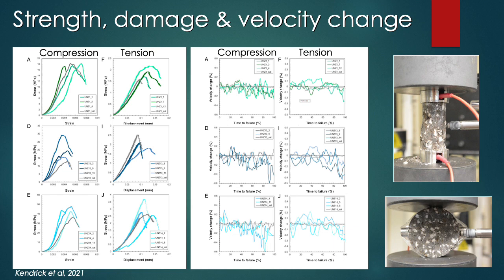During our tests, as well as monitoring the stress-strain curves as shown in the examples here on the left-hand side, we also used acoustic emission sensors to perform active surveys of our samples during testing. In this method, we use one sensor to send a pulse and the other to receive it, and we can use Coda wave interferometry to quantify the damage induced throughout the test as a result of stressing. We can use this as a proxy for the reduction in the ultrasonic wave velocity shown here on the right-hand side, which tells us when permanent inelastic strain sets in during deformation.